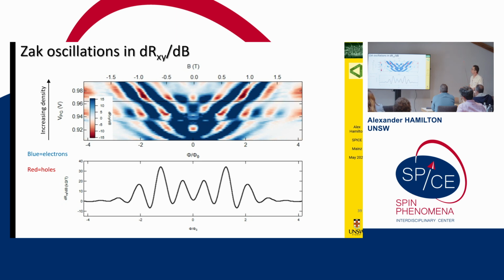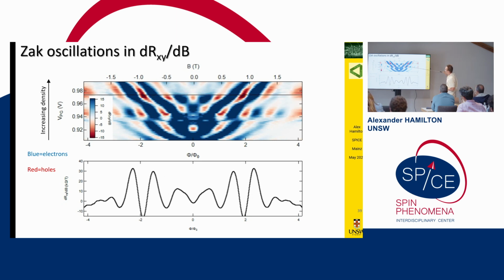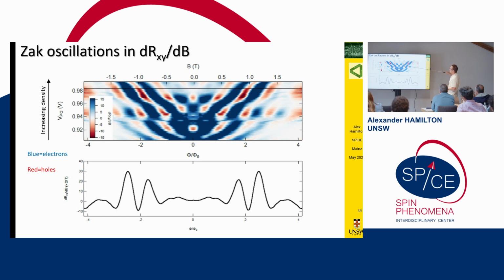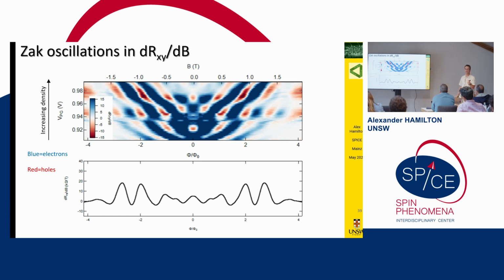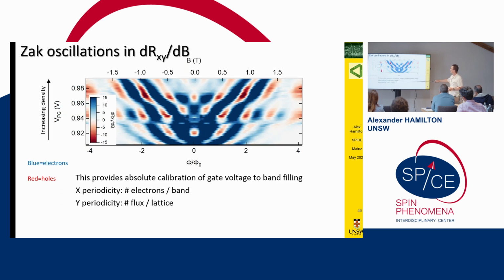And what's really nice about this is then I can say, okay, well, when I go from this point here to this point here, that's 1 flux per unit cell. I know what my lattice constant was because I built the sample, or Daisy built the sample. So I've got an absolute calibration. The X periodicity of these oscillations is the number of flux quanta per band. And the Y periodicity, this way I've got my X and Y the wrong way around, the Y periodicity is going from here to here, is I'm filling 1 band.